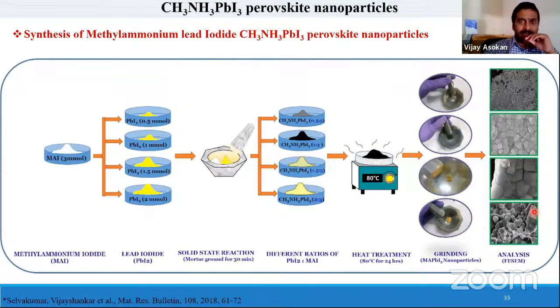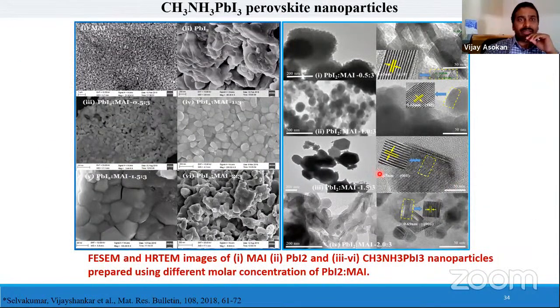different structures. We have even shown with SEM and TEM how those structures are varied when we are changing the ratio of lead iodide with methyl ammonium iodide. So here we increase iodide concentrations. That's more important here to be remembered.